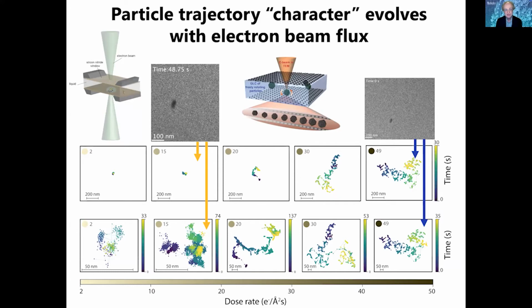In the first one, we're simply going to do the absolute simplest experiment possible. We have a gold nanoparticle in a liquid cell, and we are irradiating it with the electron beam and imaging the position of the particle. It's in water, and the particle tends to stay fairly close to one of the electrodes because of the interaction potential between the nanoparticle and the surface. And we just want to see, at first, what does the motion of the nanoparticle look like in the liquid when we are interrogating it with the electron beam?